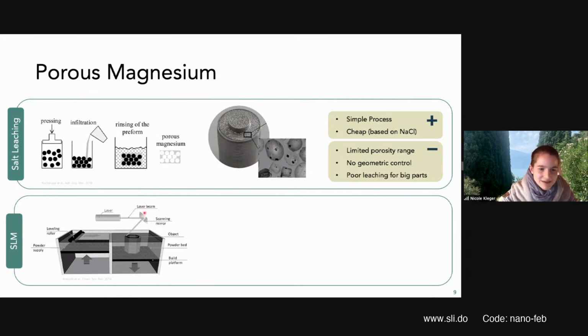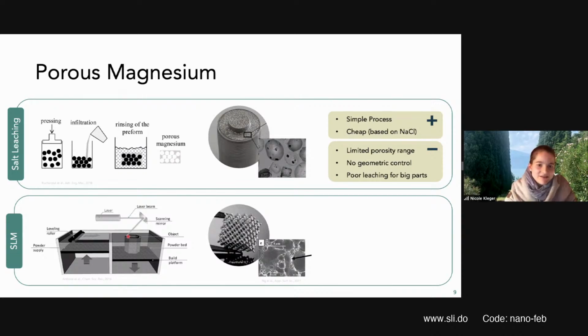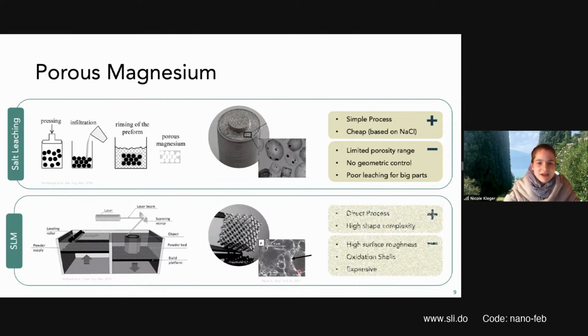Oh, I didn't explain to you how SLM actually works. So we have a powder bed of magnesium powder, and the laser is actually melting layer by layer and building up the object in that way. So if we look at the real parts by SLM, they look super fancy. We can control the shape and everything. However, if you look at the microstructure, what you find here in white are magnesium oxide shells. So they are not broken up by the process. So the part is actually a composite material. And this has really severe consequences for the mechanical properties, but also the degradation properties.